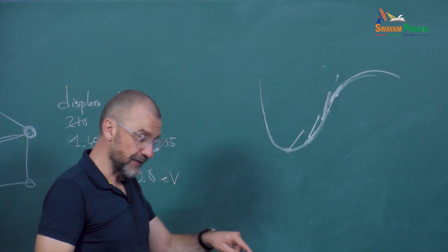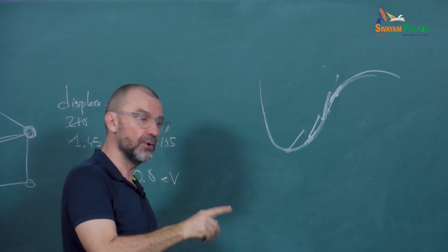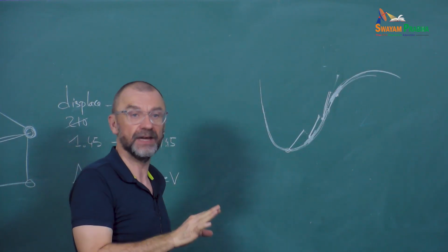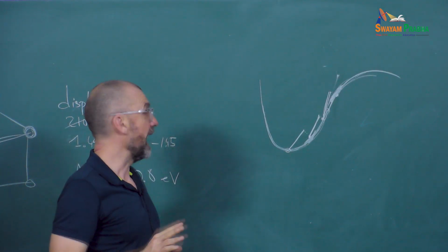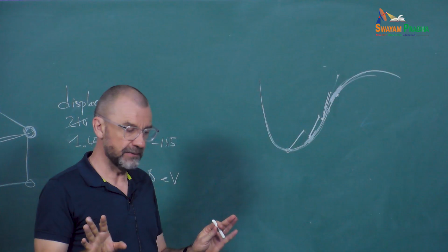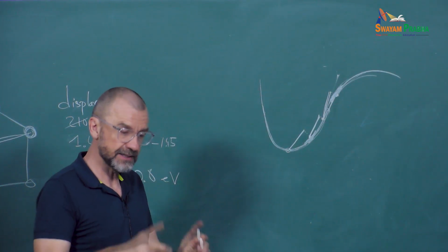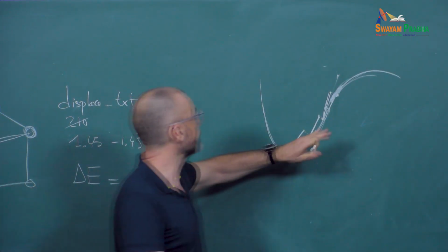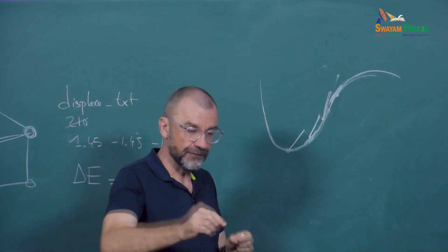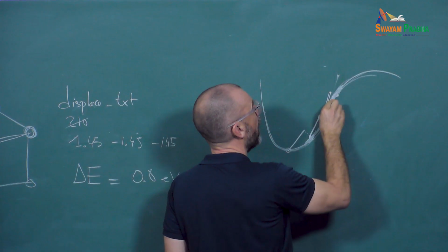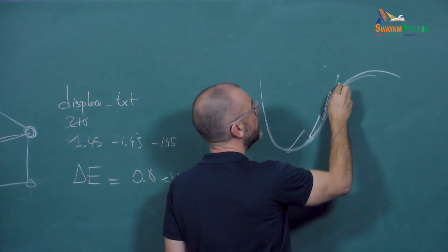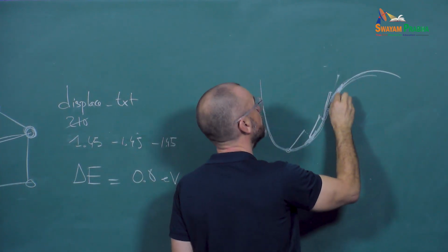Once I find a negative eigenvalue, I follow the corresponding eigenvector. So it's going to be a specific displacement, and I do that because there's no mathematical theorem to show it. But in practice, what Normand Mousseau and others have shown is that I still do finite steps, but now always along the eigenvector of minimum eigenvalue.